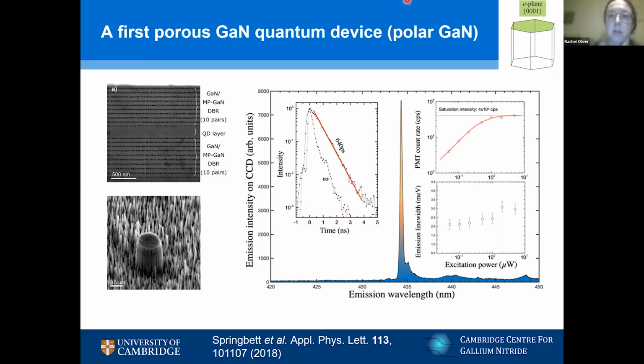Yeah, a really good question. So the thing about the nitrides is, yes, we'd love the defect density to be low, but it's not. So in a way, you're living with the defects come what may, and if you can find a use for them, you're kind of winning. The other thing I would say, though, is there are a lot of techniques and a lot of art and handicrafts that we have developed over the years for reducing the dislocation densities in these materials.